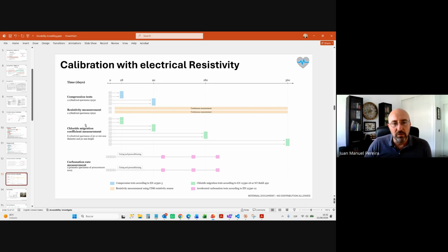Usually these chloride migration or carbonation rates are accelerated tests that work well at 90 days. Then there are non-accelerated tests that are a bit more trustworthy, where you need to wait for 180, 360 days or so, half a year, 1 year, even 2 years. Doing this type of test is okay for design, but a 2-year-long test is not at all okay for control of the site. You cannot take a sample and say let's see how this works in 2 years,